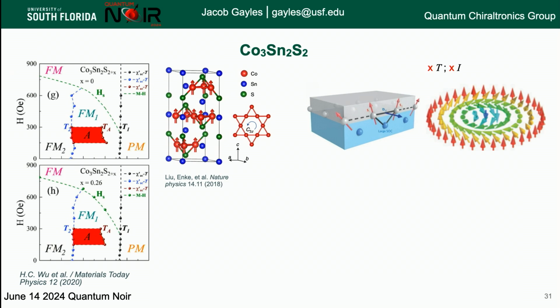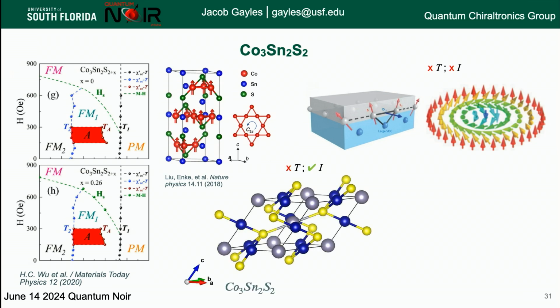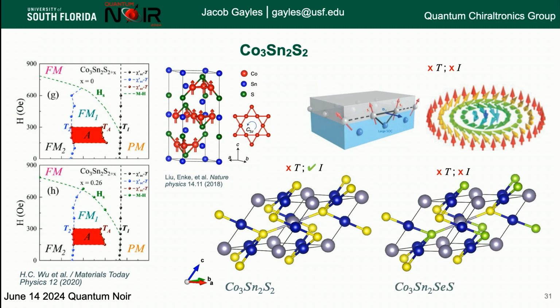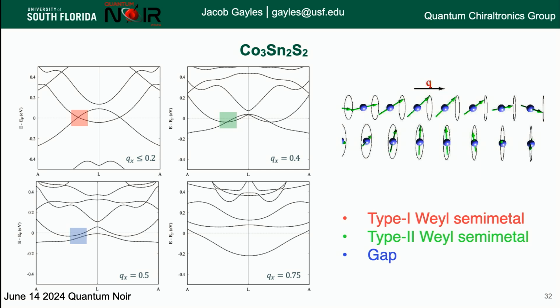The main thing that we said earlier, right? You need to break both inversion symmetry and time reversal symmetry to get those skyrmions. And this cobalt tin sulfide does not do that, right? However, I have a very dedicated student, and his idea was that we break that inversion symmetry by just chemically changing the atoms there. And so we did this, but one thing that we did was we looked at the magnetic textures in this material to see how the Weyl points behave.